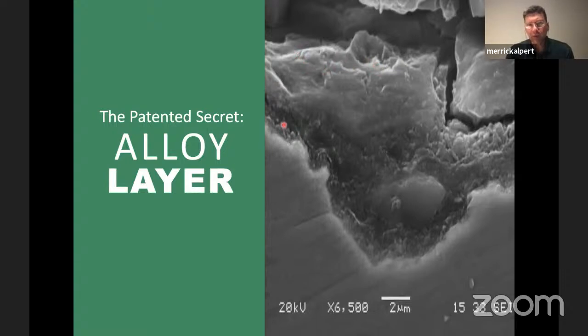Most importantly, look at this dark area, where the Eoncoat has touched the steel when it was wet and then dried. That dark area right there is the passivation layer. That is the area that prevents the oxygen and moisture from touching the surface of the steel. Now, that area is only about 2 microns thick at any point, but it is that passivation layer that prevents the steel from corroding.